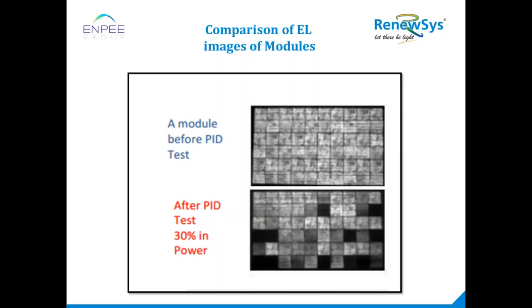Basically, the basic function of a solar module is not just to get protected from PID, but to generate at its maximum when these modules are installed in the field. So if we increase the thickness of the EVA, the opacity is going to increase, thereby the transmittivity is going to decrease, which makes the performance of the solar module go down. So that is not a viable option, but protecting it using encapsulants like polyolefin is a better option.